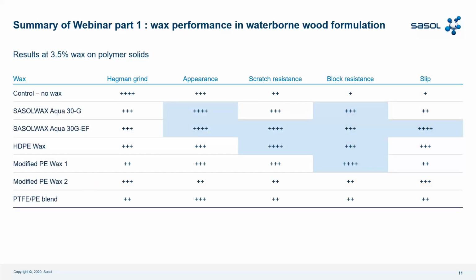These are the results that we showed in the second webinar. You can see that Sasol Wax Aqua 30G and Sasol Wax Aqua 30G-EF, the two modified Fischer-Tropsch waxes, ground and extra ground, obtain very good results in a water-based system. For appearance, scratch resistance, block resistance, and also slip, they achieve the best results.